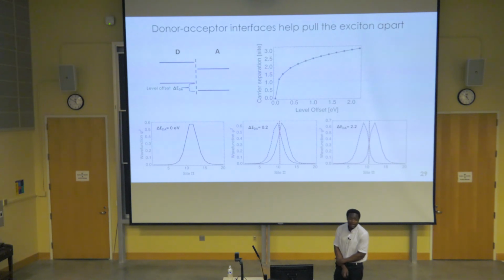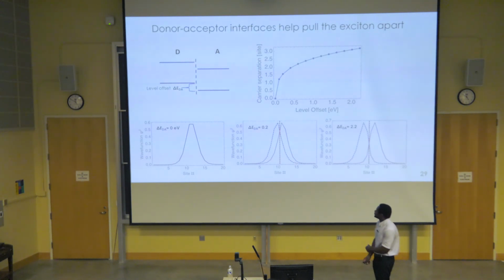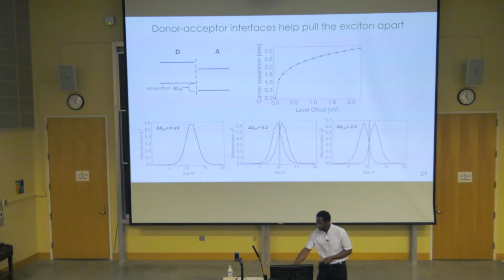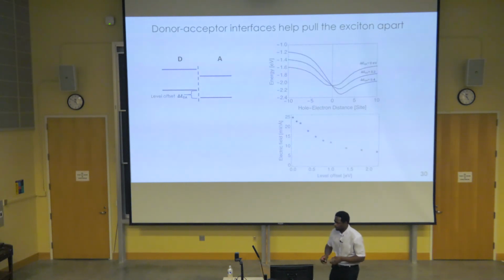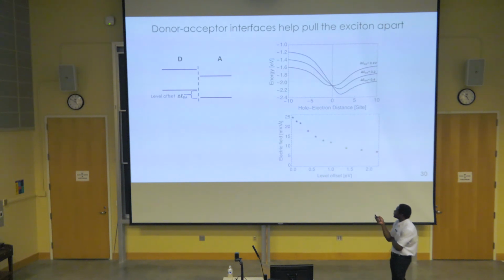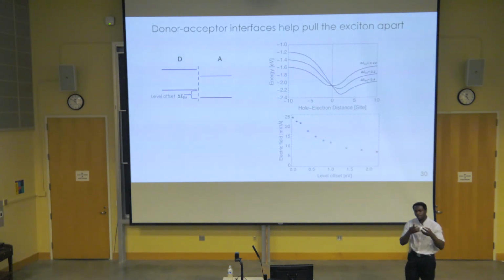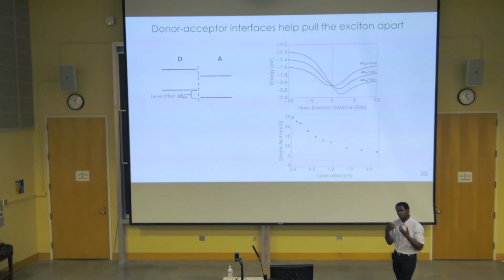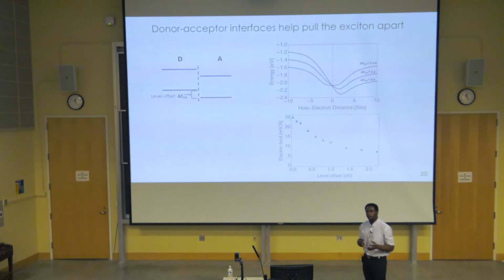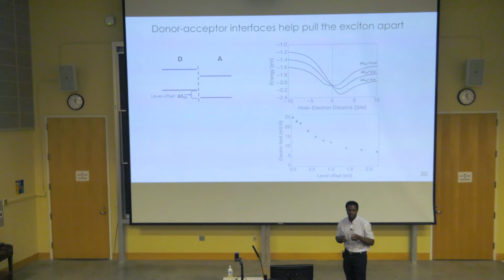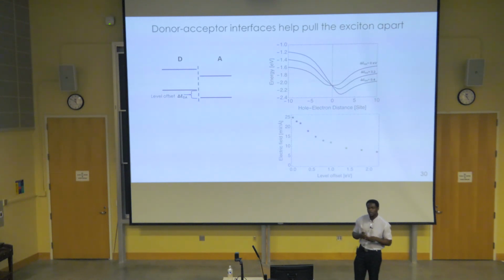Yes, exactly. This figure shows that you can obtain charge dissociation and separation by just applying an external field, but you require a pretty large field in order to obtain that. And the reason why it is important to migrate to the interface is that the exciton, not the charge carrier, has to migrate to the interface.